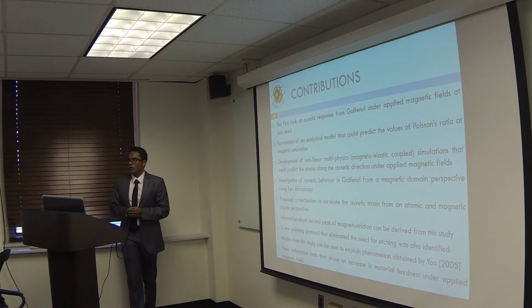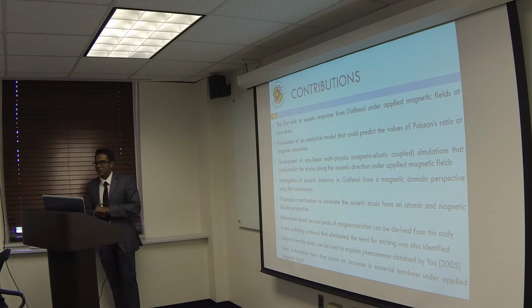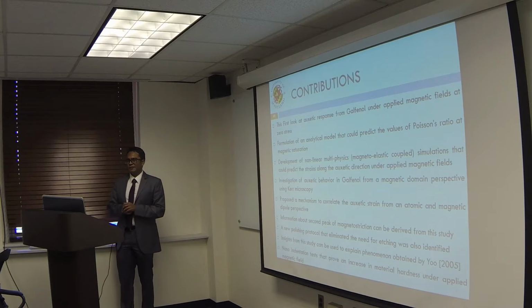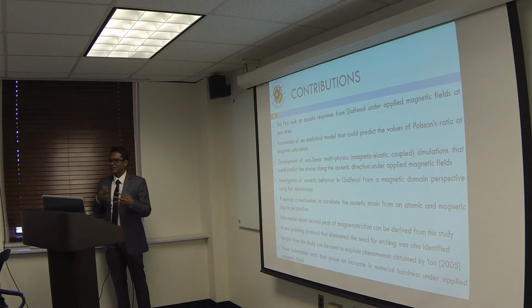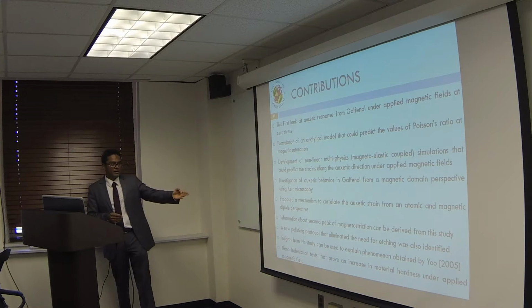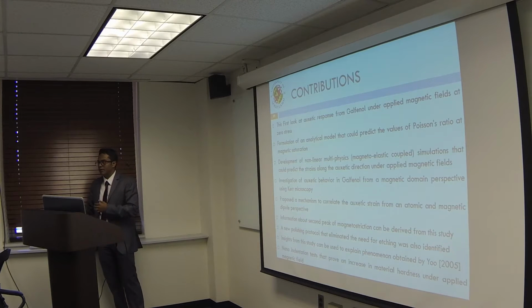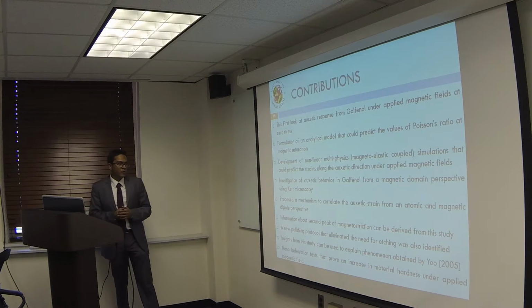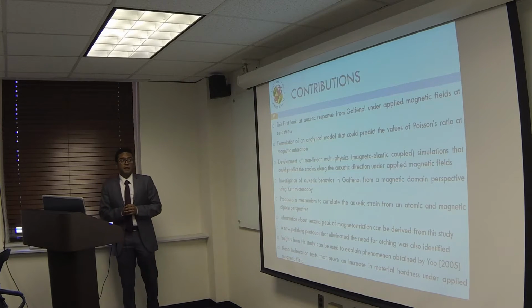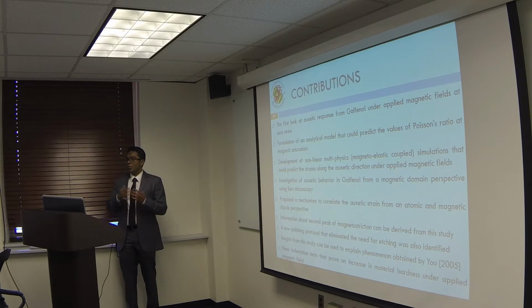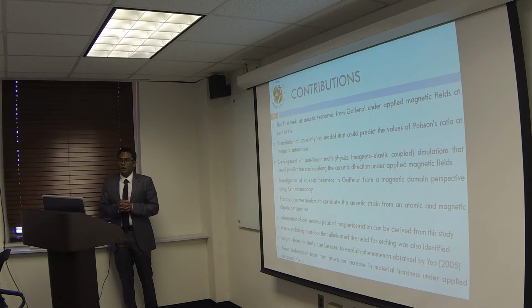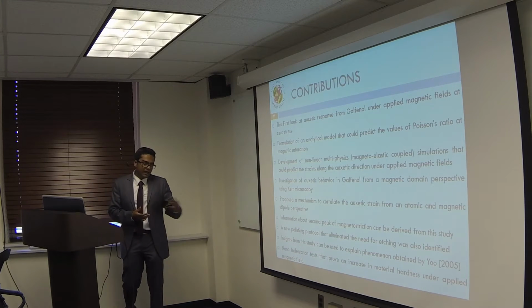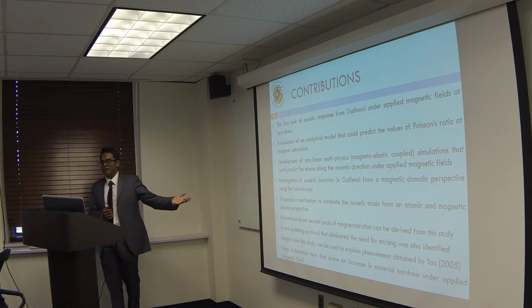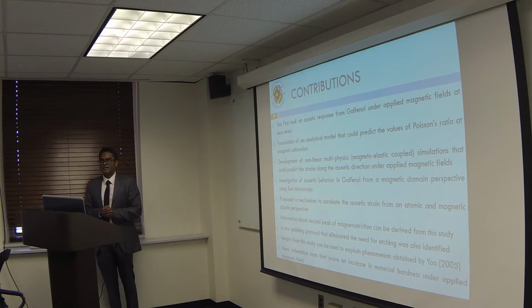I also came up with a new protocol for polishing. Traditionally, when you polish for MOKE, people have been using acids to etch the sample. This eats away a lot of material, and your sample is not the same before and after MOKE. But I was able to come up with a protocol where I can eliminate the use of etching when you polish for MOKE. And this study was able to give more insights into why Dr. Yoo was seeing lower values when he was using a DC magnetic field while doing tensile tests. And finally, nano indentation tests under the application of magnetic fields. This is something that nobody has ever done before.